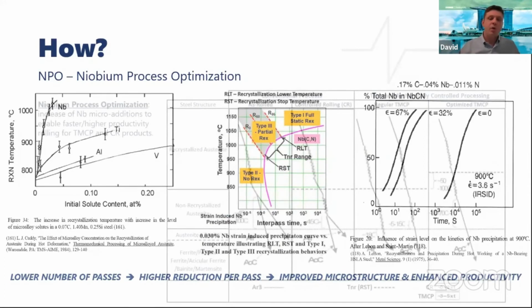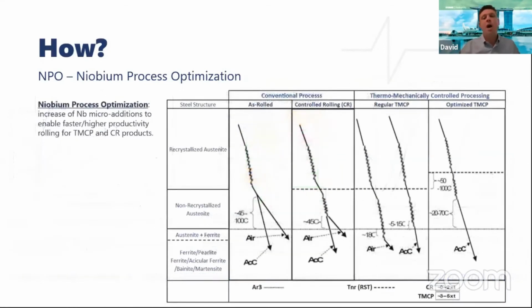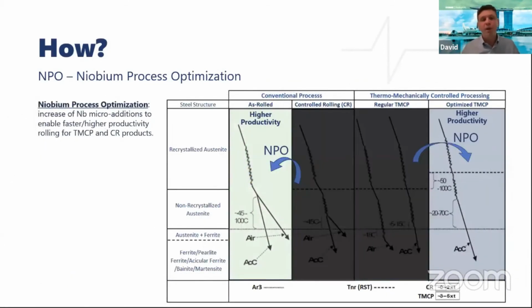In summary, what we're trying to say is that some controlled rolling non-microalloyed products could be shifted to as-rolled or conventional rolling by adding niobium, and some current TMCP products such as high strength structural steels, API steels, can be shifted to an optimized TMCP with higher productivity by applying the NPO concept.